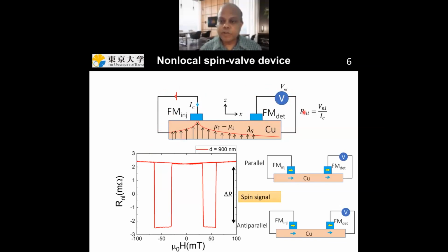You can also define a resistance, which is basically normalized to your voltage. When these 2 ferromagnets are parallel, you will get a positive non-local resistance, and when they are anti-parallel, you will get a negative non-local resistance. The difference between these 2 resistances is called the spin signal.